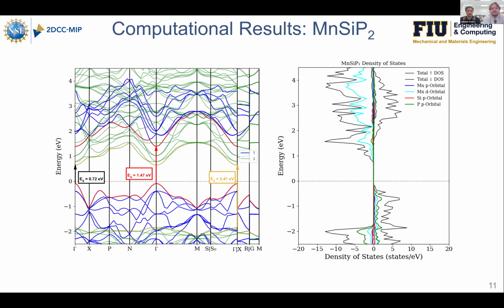Moving on to the manganese silicon phosphide, we can see a bit more complicated band structure and density of states. And that's actually because we expect this material to exhibit some magnetic properties. So you actually have to do a special kind of calculation called a spin polarized calculation. And that separates out spin up and spin down states for the electrons and considers them individually. So on the left here, we have the spin up states highlighted in blue with the conduction and valence bands highlighted in red, and then the spin down states highlighted in green, conduction and valence band highlighted in yellow.